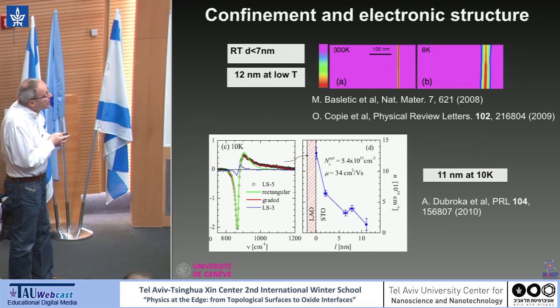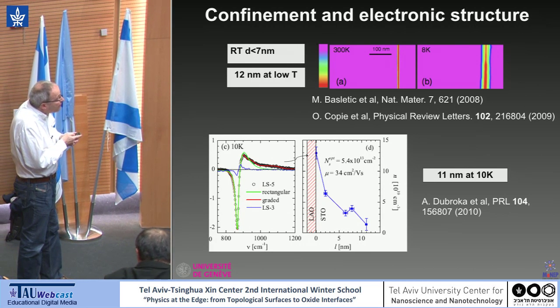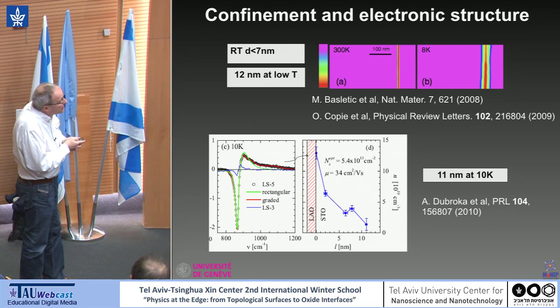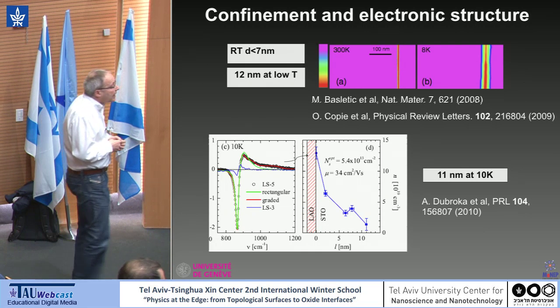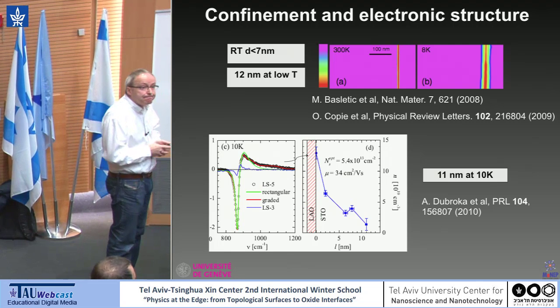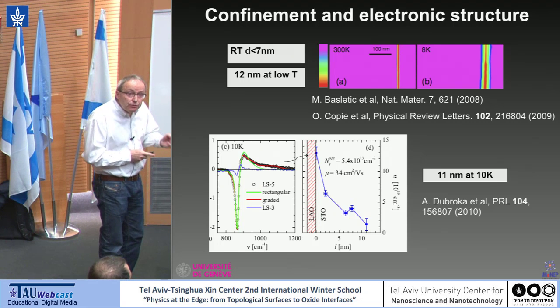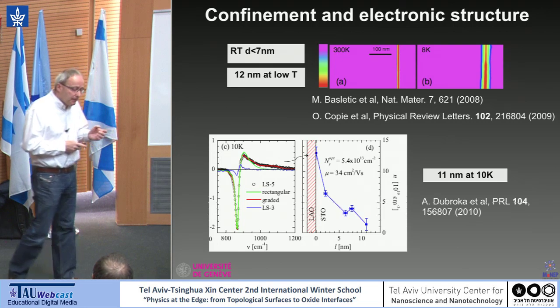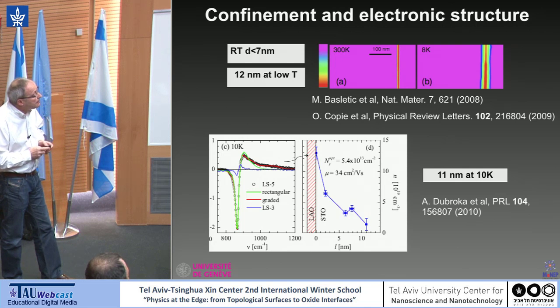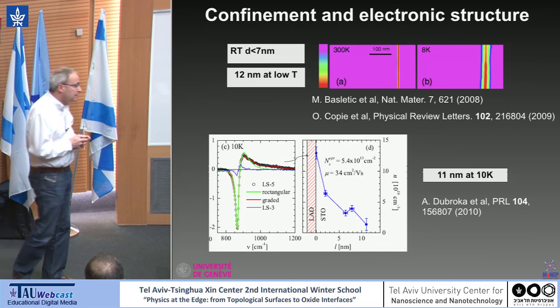And from this analysis, they could extract a profile for the carriers. And again, they find something around 11 nanometer at low T. In Geneva, we use superconductivity to determine the thickness of the superconducting layer. And I will explain this because I will need this a little bit later.